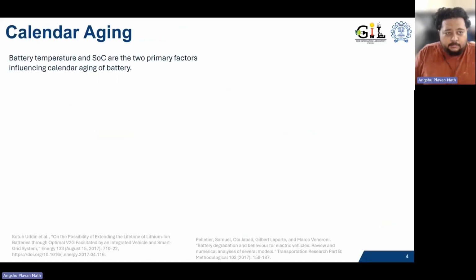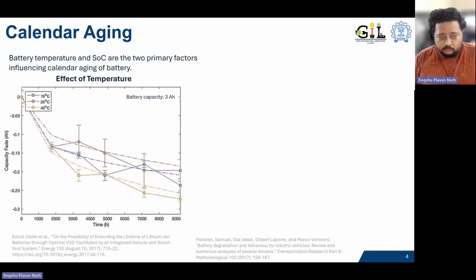Now, coming to calendar aging, battery temperature and SOC are two primary factors that influence the aging of the battery. If we look at the effect of temperature, if we store a battery at higher temperature, the degradation is faster. So here it's an experimental study where three different samples of a 3 ampere-hour battery were stored at different temperatures. When a battery is stored at a higher temperature, at 45 degrees Celsius, the capacity fade was much higher. And the capacity fade was minimum when the battery was stored at normal temperatures.